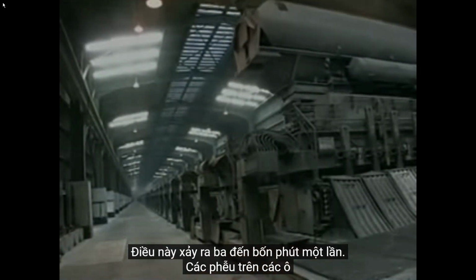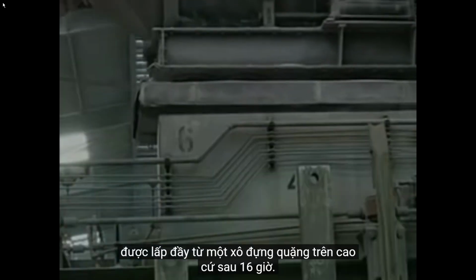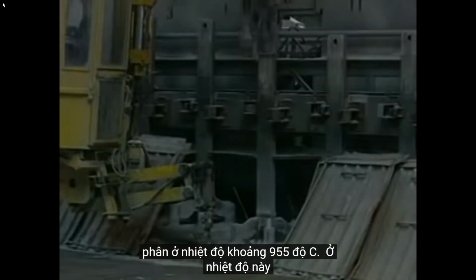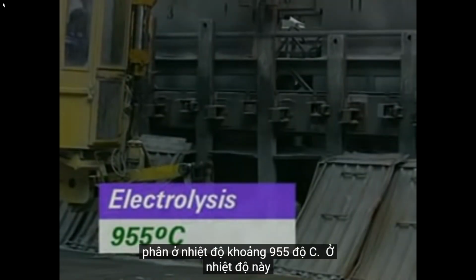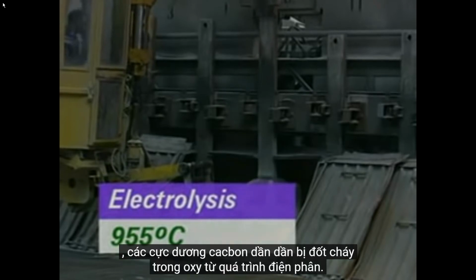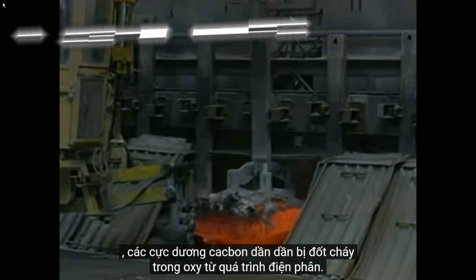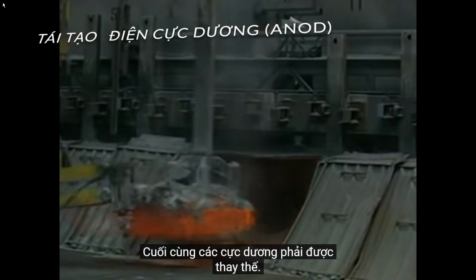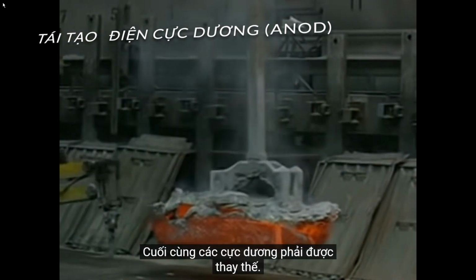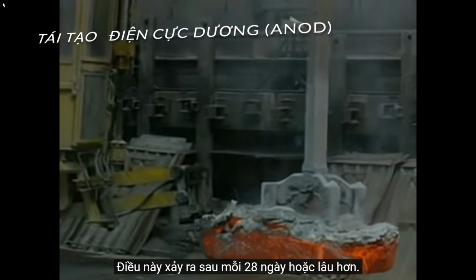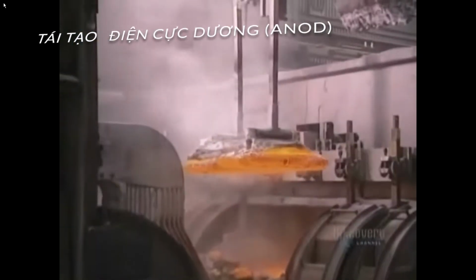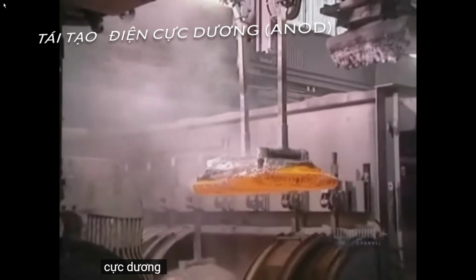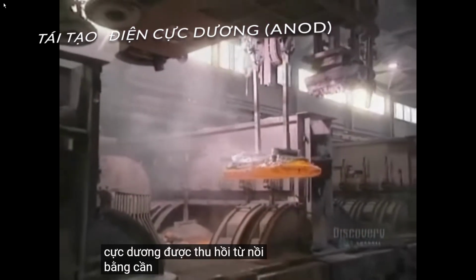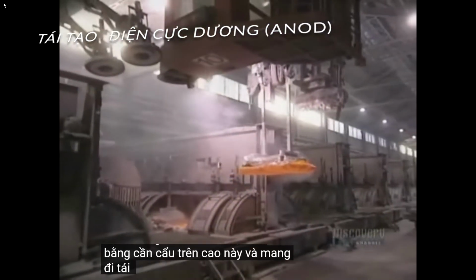The hoppers on the cells are filled from an overhead ore bucket every three to four minutes. The electrolyte is at about 955 degrees Celsius. At this temperature, the carbon anodes gradually burn away in the oxygen from the electrolysis. Eventually, the anodes have to be replaced, and this happens every 28 days or so. Spent anodes are recovered from the pot with this overhead crane and carried off to be recycled.